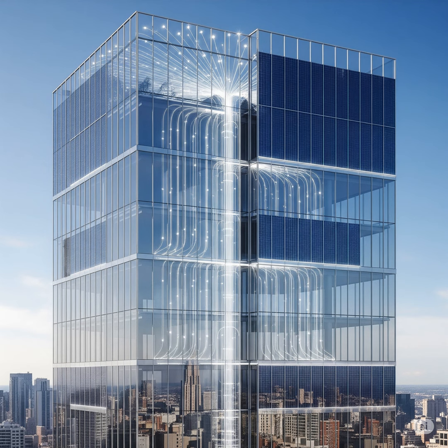But here's the really clever part. Even though they're adding these color layers, the power conversion efficiency of the window remains almost constant, regardless of the color being displayed. Wait, really? Adding color doesn't hurt the power generation. How? Because the MIM structure is typically applied to the backside and primarily affects the areas between the active perovskite microcells. It's managing the light in the non-generating parts so it doesn't really interfere with the light hitting the perovskite itself. That is a huge win for design integration.